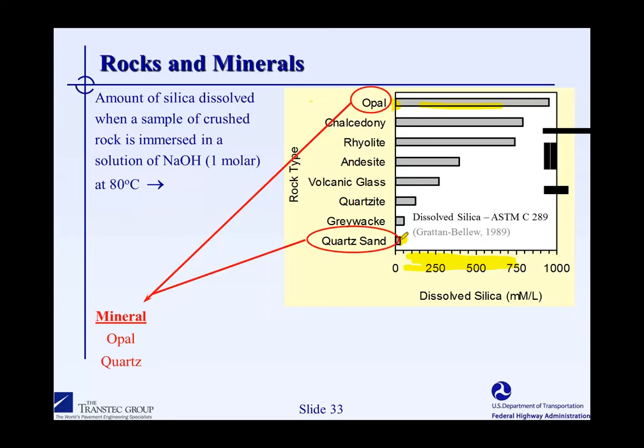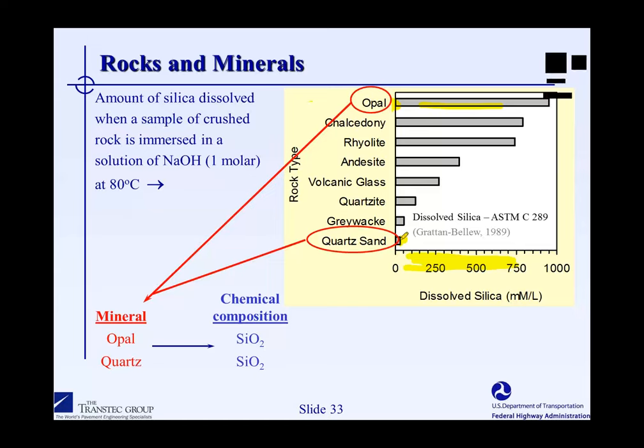If we look at the chemistry of the minerals opal and quartz, quartz is almost entirely silicon dioxide, SiO2, silica, and opal is predominantly silica as well. They're chemically very, very similar. Opal might contain a few impurities too. Despite their chemical composition, one type of silica is highly reactive and soluble at high pH, and the other type is almost insoluble and won't cause reaction in concrete.